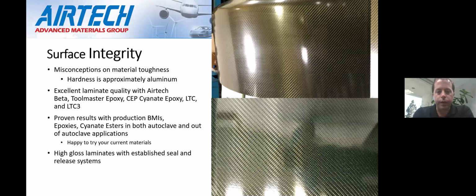Also looking at how the surface holds up. A common misconception is the material toughness. Greg mentioned it, but the material itself is approaching about the hardness of aluminum. And as many of you know, aluminum has been used for decades in the composite industry. So we've seen really excellent laminates coming off with all of our own resin systems: our benzoxazine, our Toolmaster epoxy, our cyanate epoxy, and our LTC, low temp cure epoxy systems.